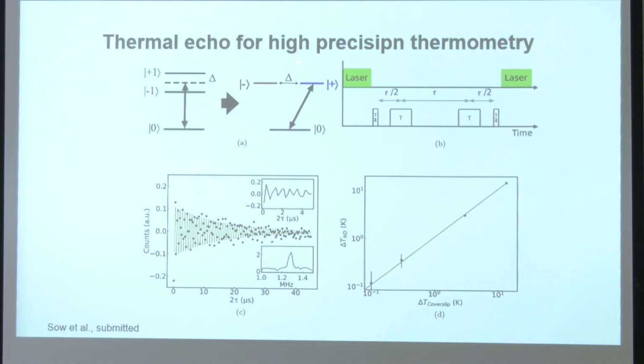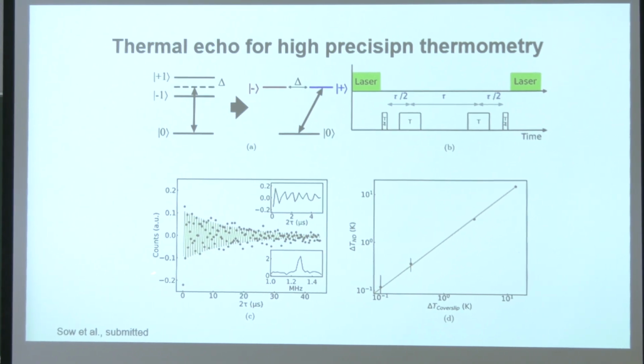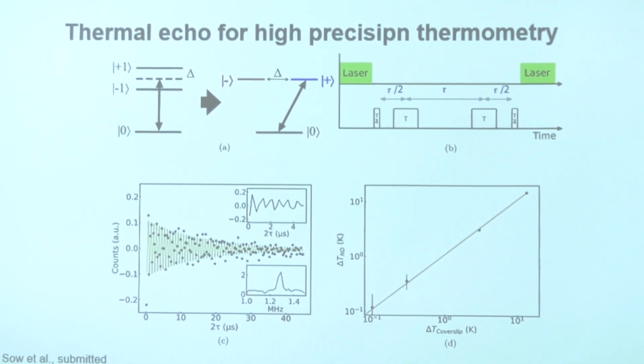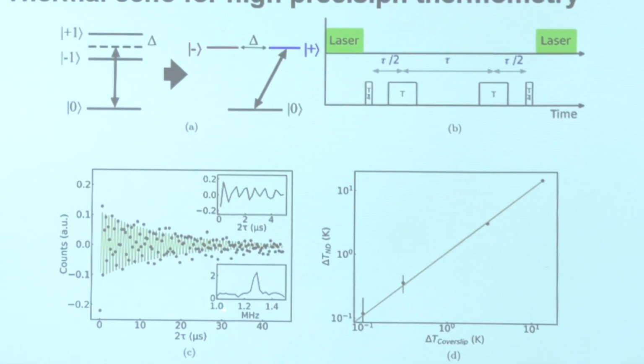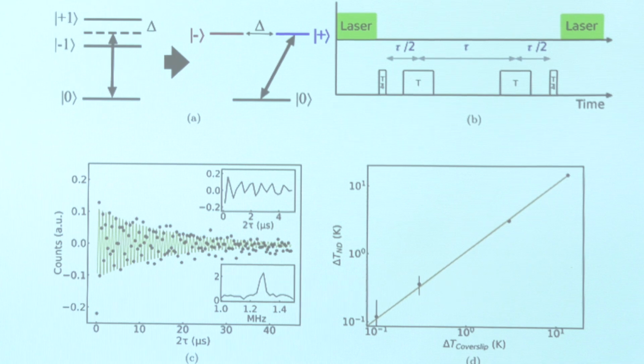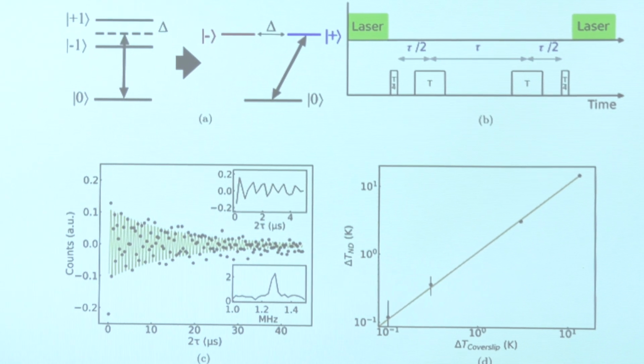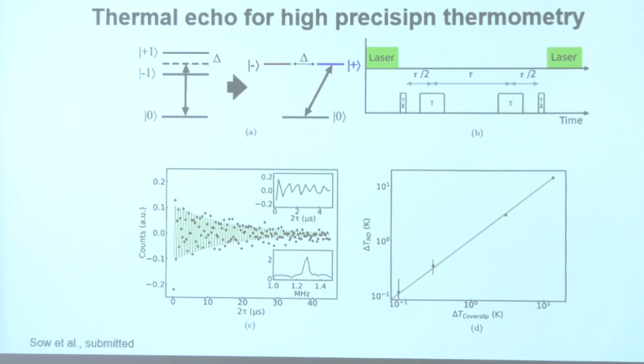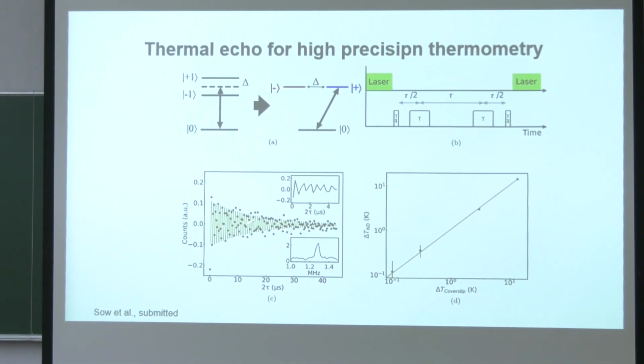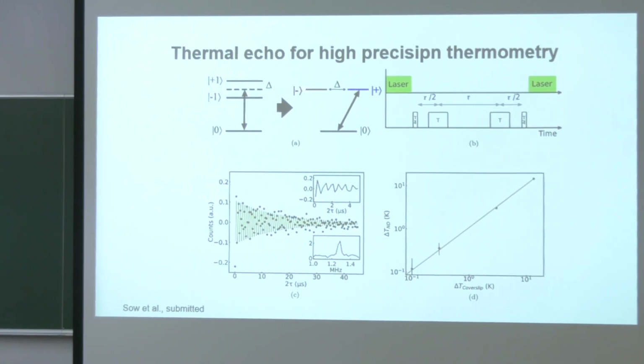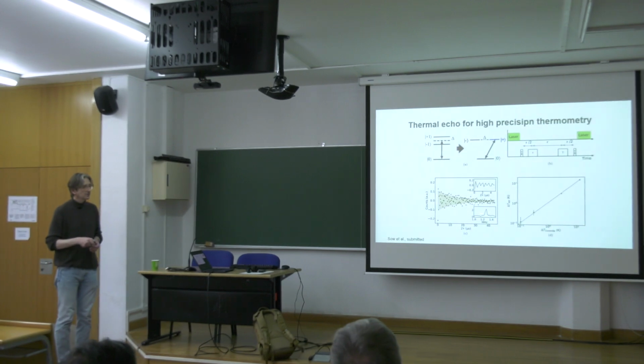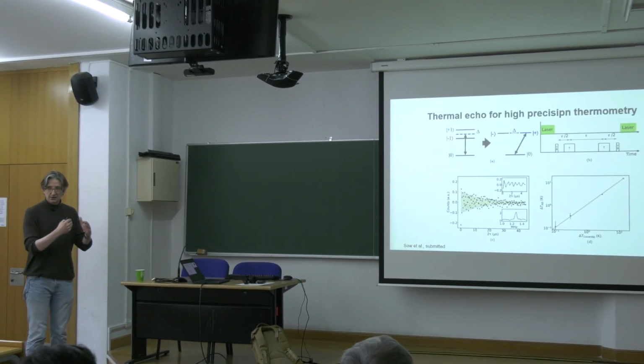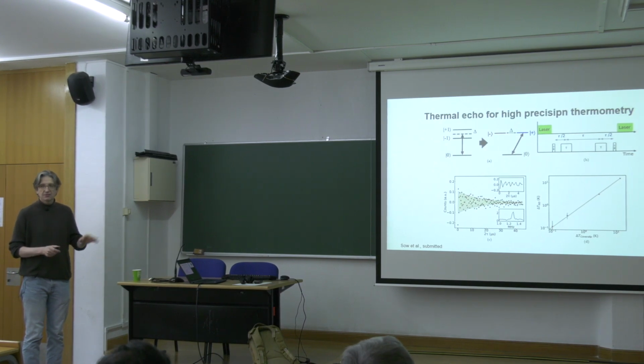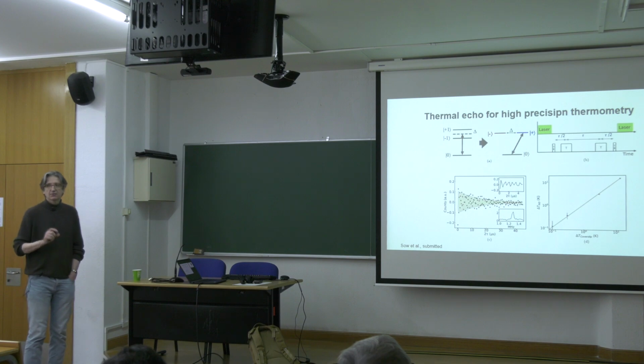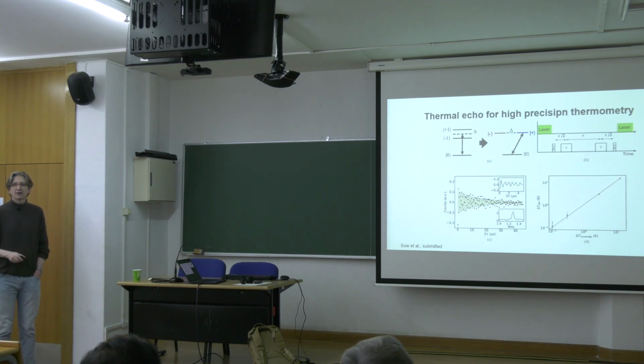And this echo, which we call thermal echo, allow you to measure the coherence which is associated with like thermally sensitive coherence on a time scales of tens of microseconds, leading to the kilohertz line width of the transition. And that was done for nanodiamonds here for the first time. So the kilohertz narrow transition and the shift of spectral line by 80 kilohertz per degree Celsius, allow you to measure the temperature very precise. They get on millikelvin precision level. Here I show you the measured temperature versus kind of temperature input in the cover glass where nanodiamonds align, and it fits very well on a straight line, and the error bar is already on a millikelvin scale of errors.